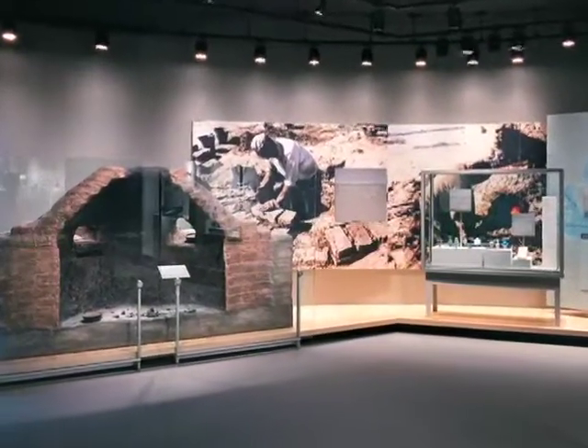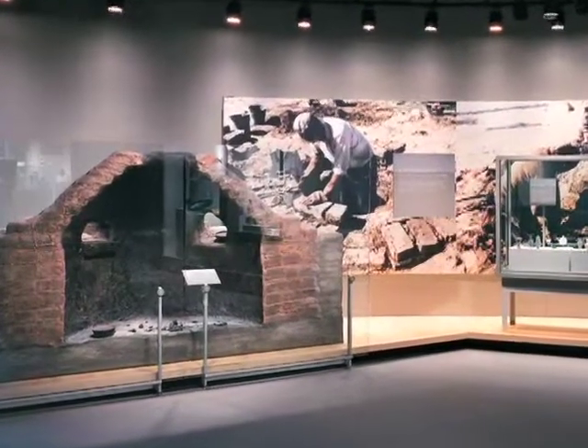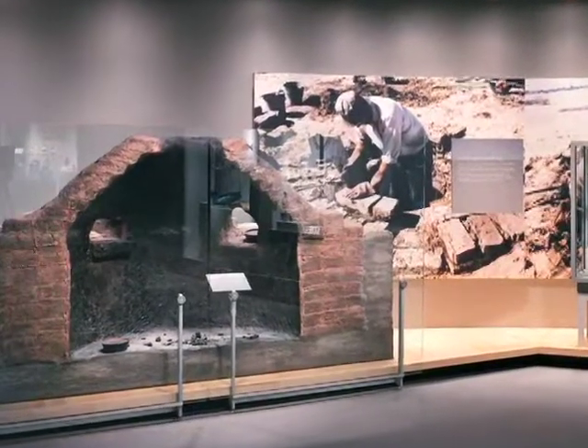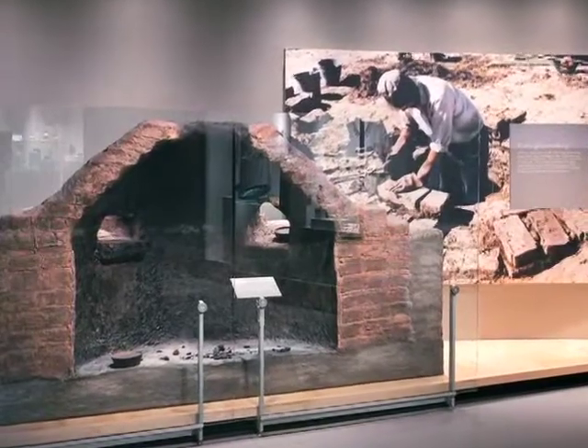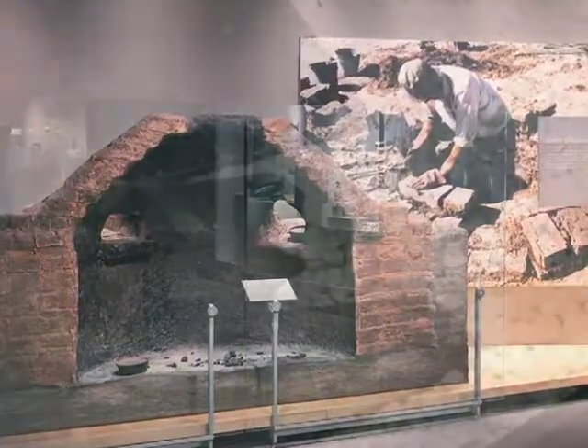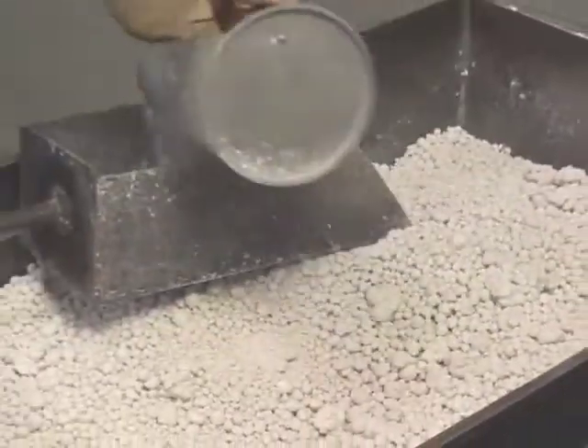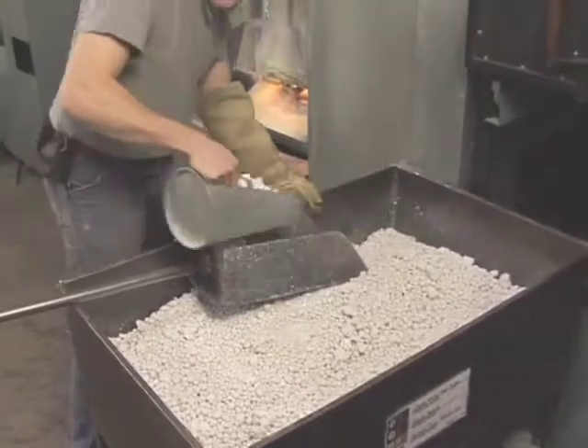What's the third ingredient? That needs to be calcium in some form — lime, chalk. And you need that because the mix of sand and the alkali flux is inherently unstable; the glass will self-destruct. So you throw in a small amount of calcium, and that stabilizes the glass, and it becomes pretty much a permanent substance.